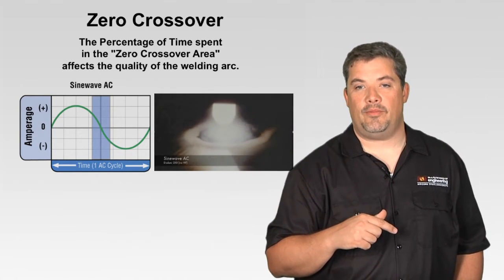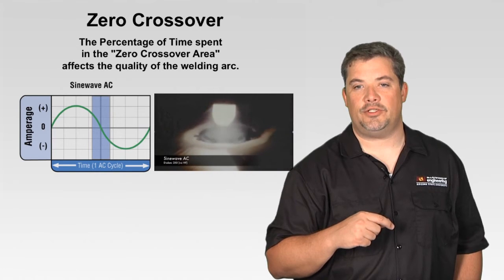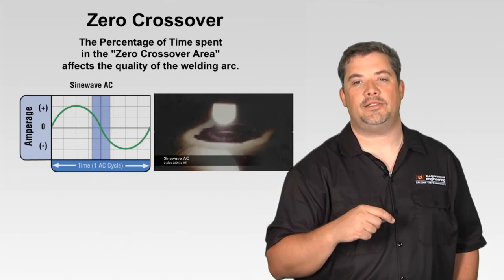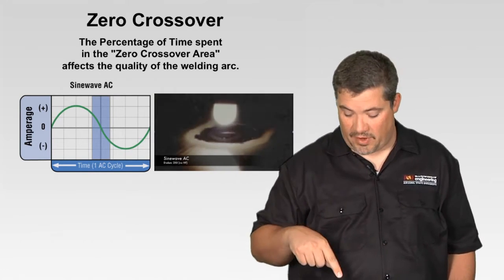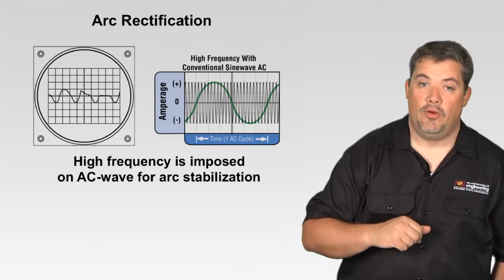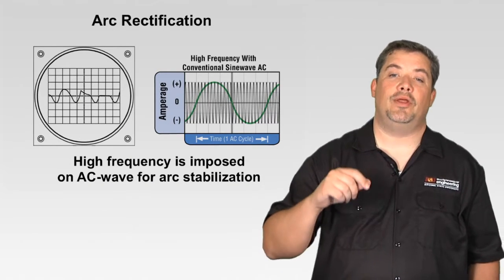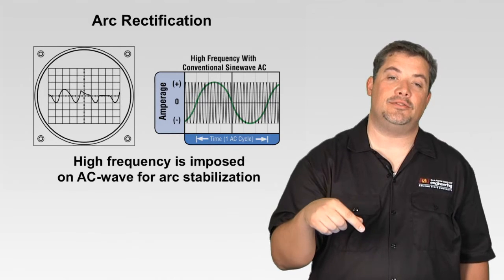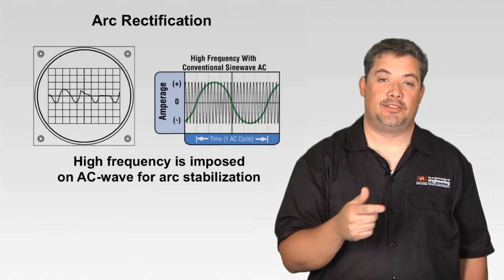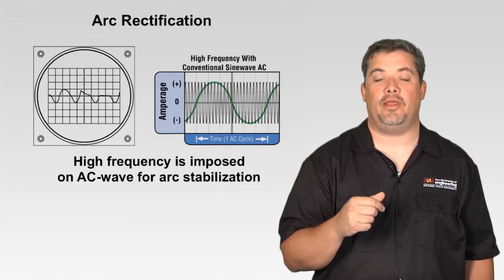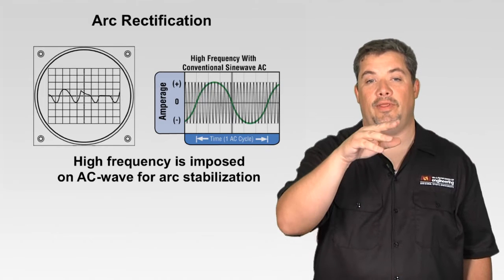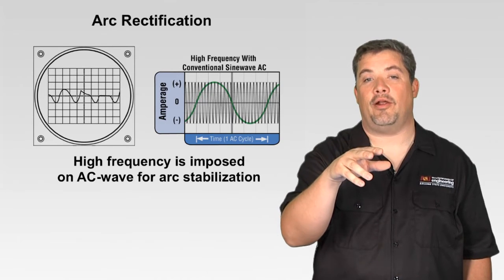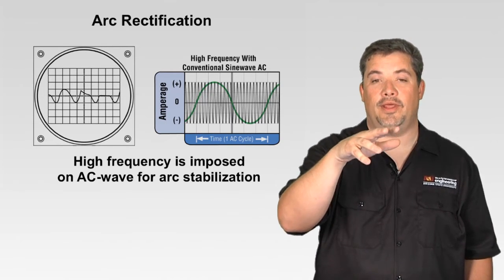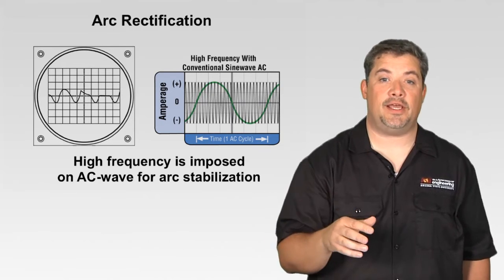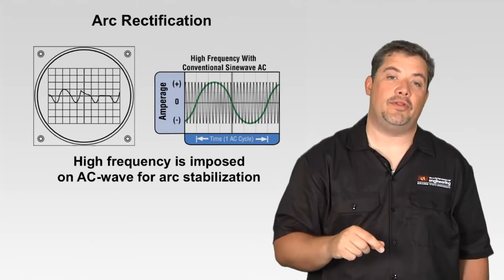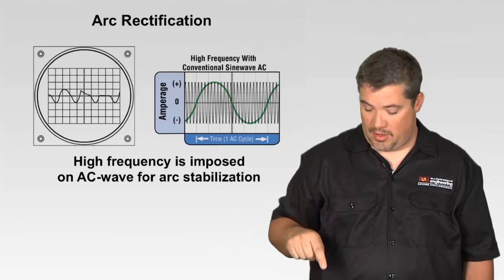In this video, I can't recall if it actually shows an arc outage. I do not think it does, but sometimes the arc will rectify and go out. Arc rectification happens when one half of those cycles misses. You can see an oscilloscope type drawing on the left where the positive half of that arc is fading out, where it's going to miss half that cycle. So we use high frequency all the time to avoid that from occurring.